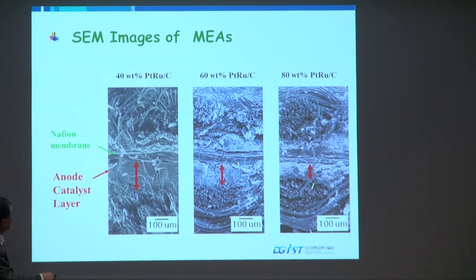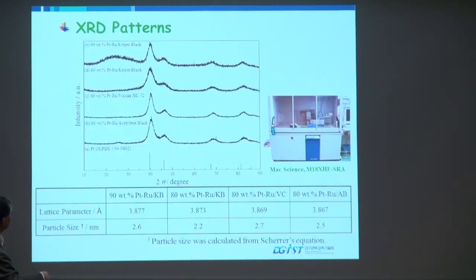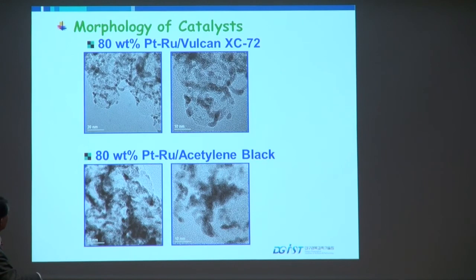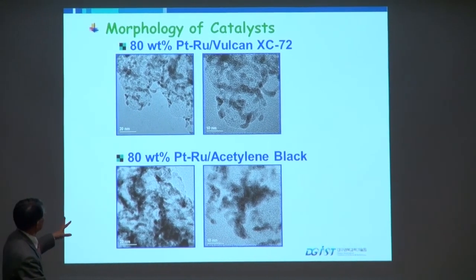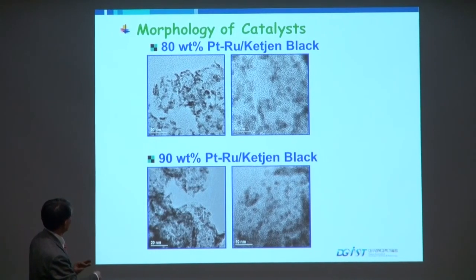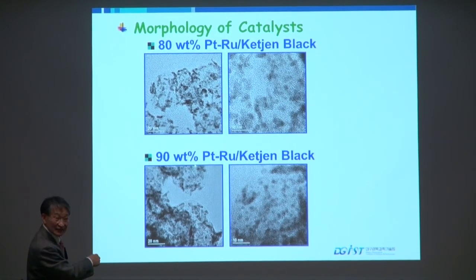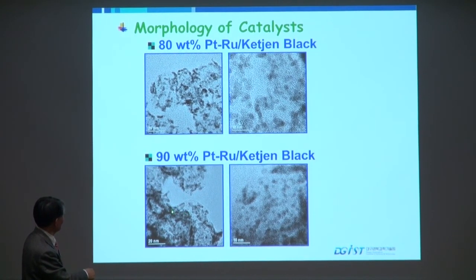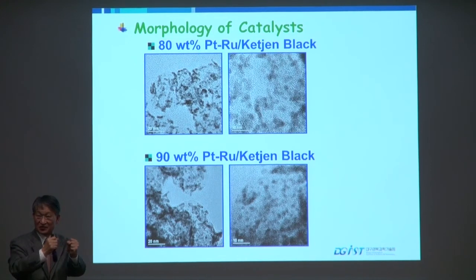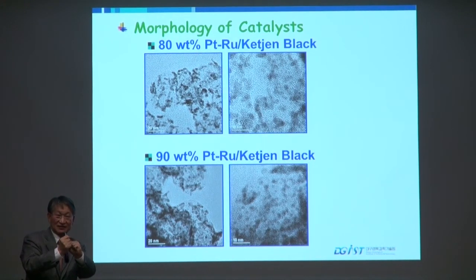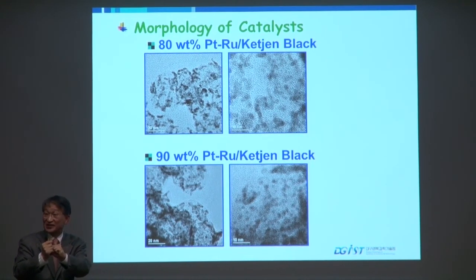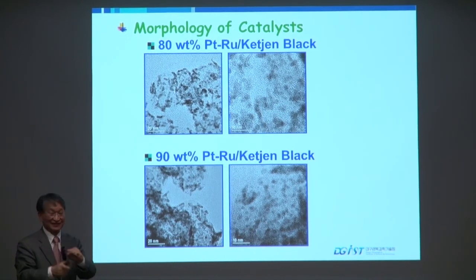So that's why we increase this much. Then the thickness of the catalyst layer is dramatically decreasing by increasing the metal loadings. Then, of course, the morphology is almost the same, but when you have 90%, then you can see all this platinum is agglomerated. They stack together. So that means the utilization is not very good at all.